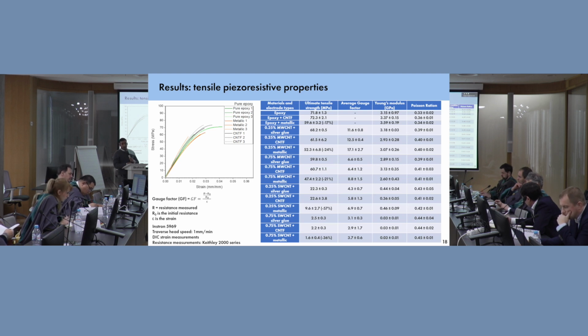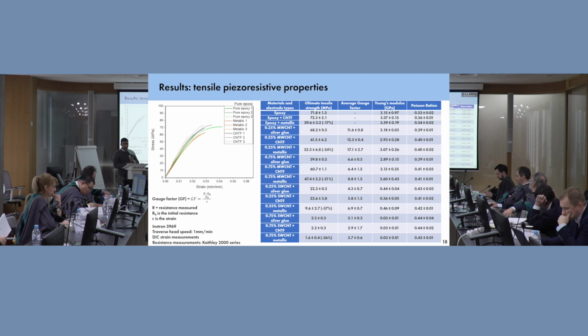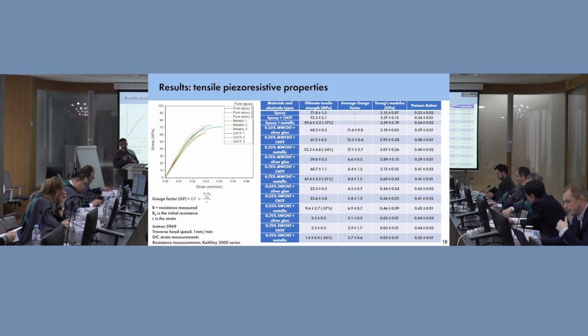As we move into our nanocomposites with an addition of carbon nanotubes in the matrix, we start to see that the UTS of our nanocomposites with or without our carbon nanotube fibers is mostly similar. It is within each other's variance, but wherever we have our metallic embedded electrodes, we have a significant loss in this strength. Our materials start to fail sooner. Now, of course, we plotted on the next slide, I will come into the gauge factors, but our Young's modulus also begins to change, as well as the Poisson ratio.